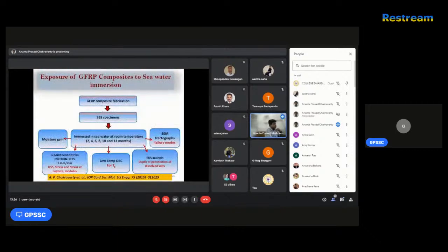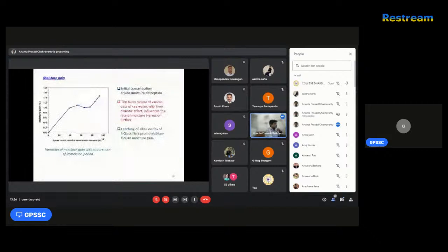So now when such materials are exposed to seawater, there are salt assisted degradations and similarly moisture induced degradations. So I prepared the specimens and immersed them for up to 1 year, and I studied their mechanical properties, the glass transition temperatures, and EDS analysis to know the depth of penetration of the dissolved salts. Then I saw the moisture gradually increased, and at a certain extent it decreased again and then increased. Generally when it is exposed to moisture, this does not happen, that the moisture absorption will sometimes decrease. So that is a very peculiar phenomenon.